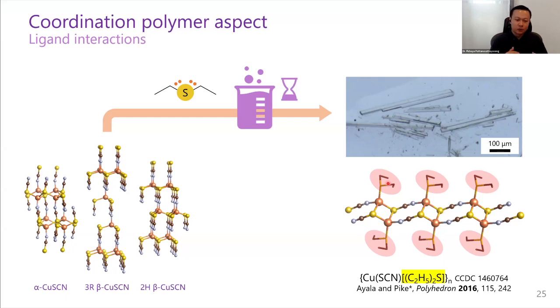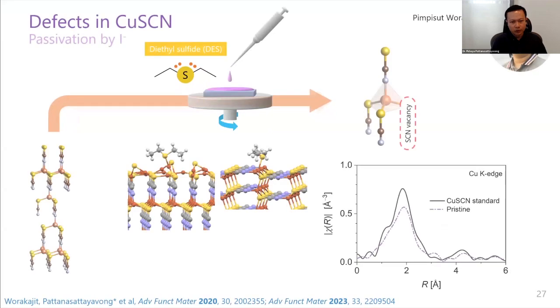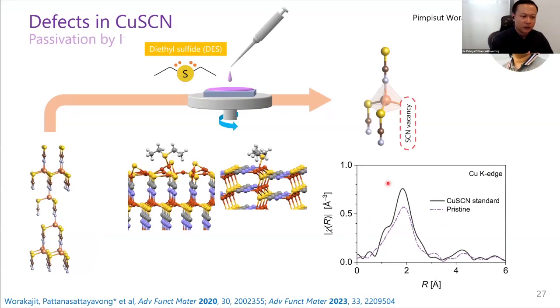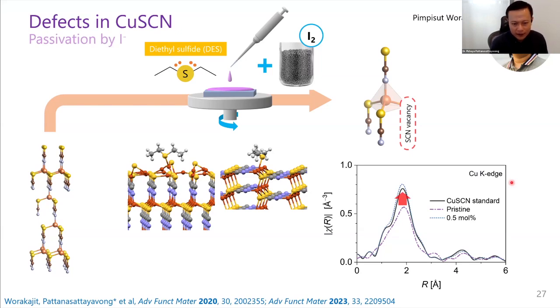Nevertheless, they can still be removed by heating, and that's the usual way we process them into thin films. The implication of this is that because of this strong interaction, during the removal it actually leaves a lot of defects inside. We showed that indeed we have thiocyanate vacancies around copper, as studied by X-ray absorption spectroscopy, and we can heal the defects, for example, by using iodide - adding solid iodine, which separates into iodide ions, and the iodide can heal the defects, recovering the coordination environment around copper.